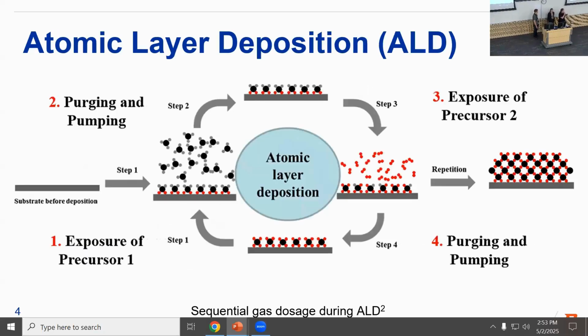So let's start off with what standard ALD looks like. The key feature of ALD is its self-limiting nature, which means that once all of the reaction sites on the surface of a substrate are saturated and a single monolayer has been formed, the reaction stops. Starting at step one, as we can see, precursor one is pumped into the chamber. It is allowed to react with the surface of the substrate and form a full monolayer.